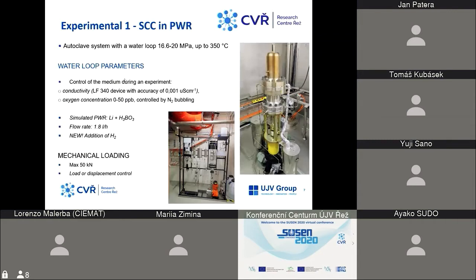So during the SUSEN project, facilities were built. The first one is, as I said, in Řež, and it is an autoclave system with a water loop, which allows us to perform tests up to 350 centigrades in the simulated water environment. We have control of the medium during the experiment. We measure conductivities, oxygen concentration, flow rate. We can also now newly add hydrogen into the system and simultaneously apply mechanical loading up to 50 kilonewtons.